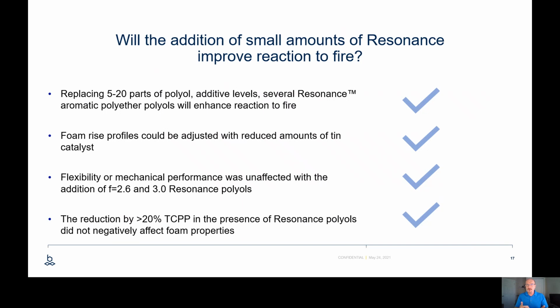Foam rise profiles were easily adjusted with small adjustments in tin. The flexibility and mechanical properties were unaffected with the introduction of the resonance materials, even when we took out some TCPP, which was a bit of a surprise because you can imagine the system is getting a little more viscous because of that. And the reduction of about 20% in the presence of polyols did not affect that foam property.